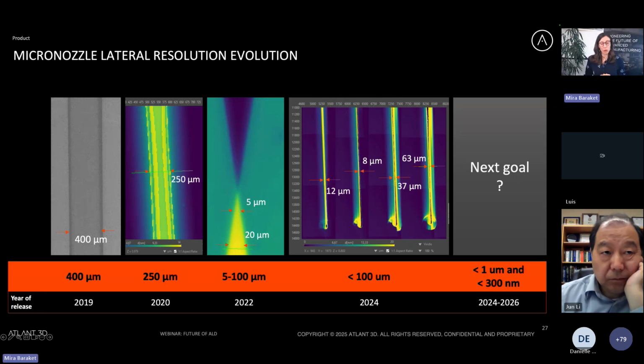And recently, we had a breakthrough in our technology, where we were able to introduce a new nozzle type that will allow you to have a variable line width with one same nozzle. So what this means is that you can create your patterns with different line widths on the same wafer, using the same micro nozzle. And we are constantly working on improving our resolution, and we do have processes and technologies that we are confident will allow us to go beyond the 1 micron resolution.